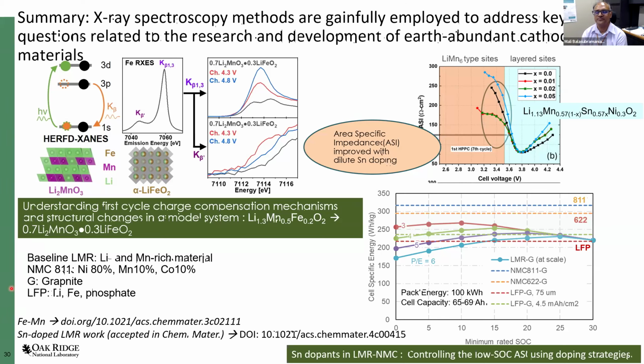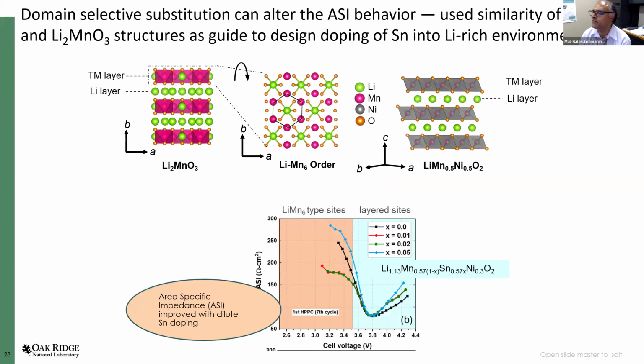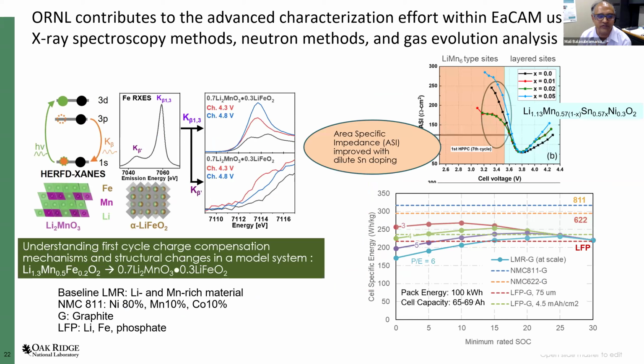Thank you. All right, we have a question whether the dopant segregation towards the grain boundaries improves the material's electrochemical performance, or is it a feature or a bug that the tin is going to the grain boundaries? I mean, we believe it's an important feature that we design. We feel proud that we were able to design it, right? We wanted to modify the response for the low voltage sites, and we believe that we have done that by tin doping.